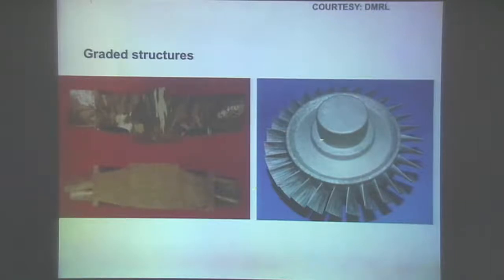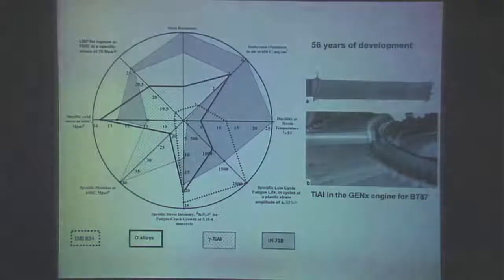So you can control heat extraction during solidification such that you have fine grain structure in the center and coarse grain directionally solidified structure on the blades. So again, those of you who work in solidification can look at this engineering technology which controls the heat extraction during solidification on just one part of the integral casting that you're making while providing a fine grain structure in the center. So metallurgy is not just solidification, it's not just chemistry, it's not just mechanical behavior. It's a control of heat transfer and a million other things to manufacture a part with graded structures that can meet improved performance requirements. What are new materials?